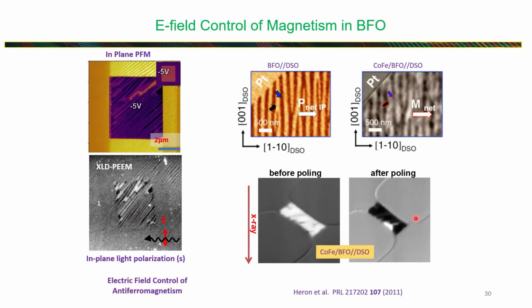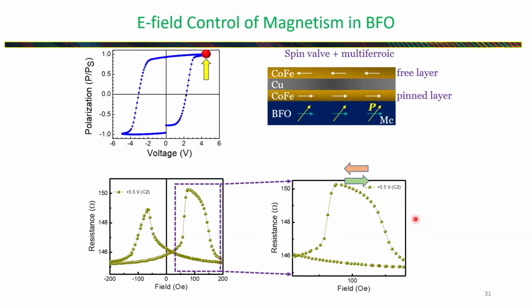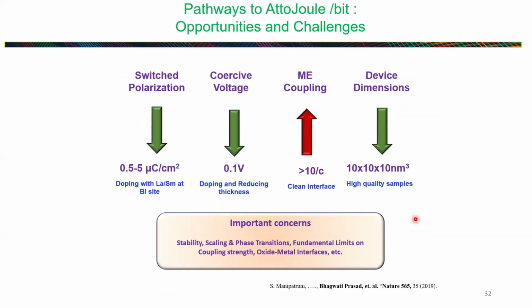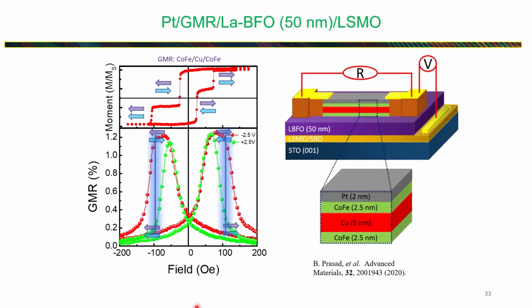Okay, so we have actually made some sort of spin valve on top of that, a GMR stack. And with the GMR stack, basically what we found is, so I directly come to here. Here we have used a layer of the LBFO, and we make a GMR stack on top of that, which is basically a spin valve where you have cobalt iron, copper, cobalt iron, and platinum. Both have the same thickness, 2.5 nanometer. The bottom cobalt iron here is actually coupled with the LBFO, and hence because of exchange coupling, the coercivity has gone up, as well as there is RKKY coupling certainly. So what happens is that when you apply electric field, you can basically modulate this coupling strength. Okay, so you can go from anti-parallel to the parallel state like that.